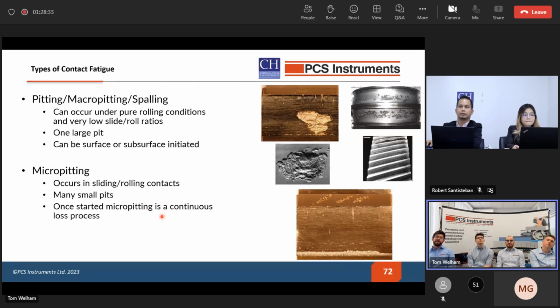Micropitting, on the other hand, happens on a much smaller scale, often on the same scale as the asperities. So the asperities are the peaks of the surface roughness that are in contact, and they're measured in about tens of microns, and these can form a dense network of pits and cracks and create a continuous removal of material. And the surface of a micropitted surface can end up being quite dull and matte in appearance.